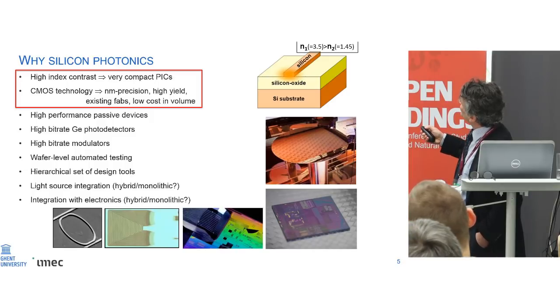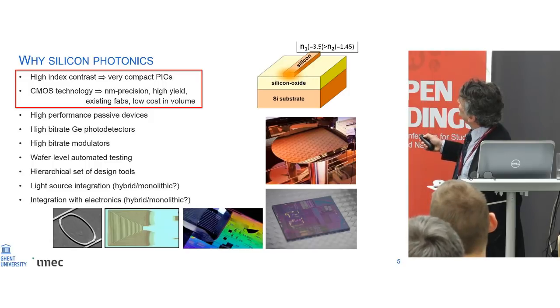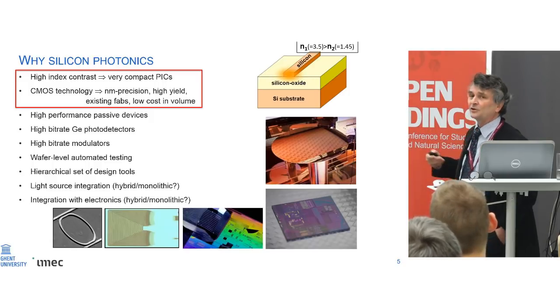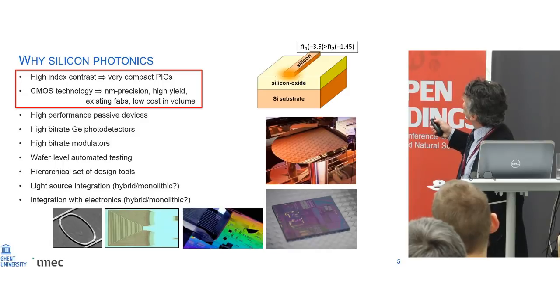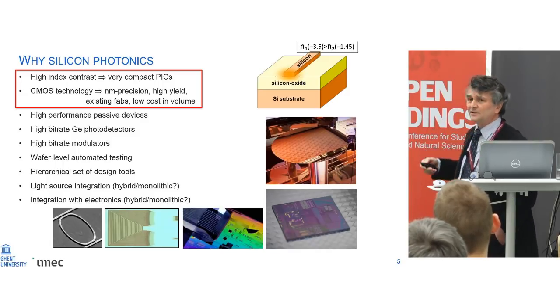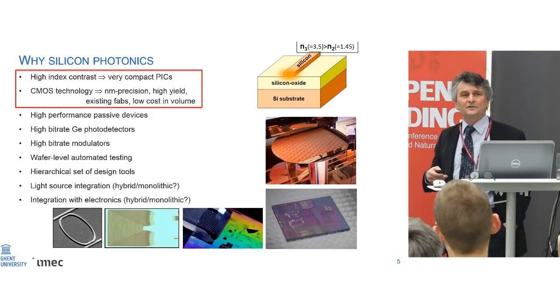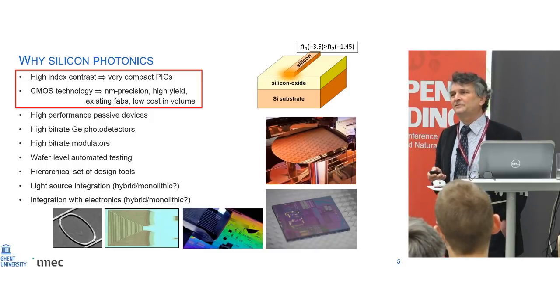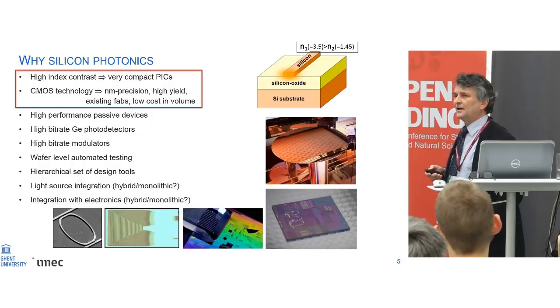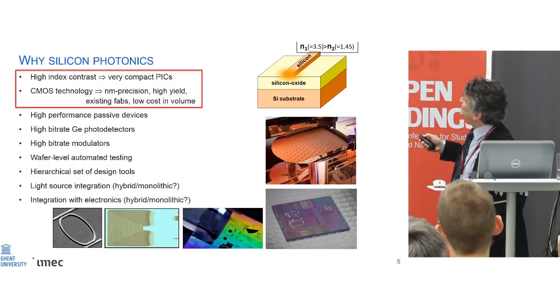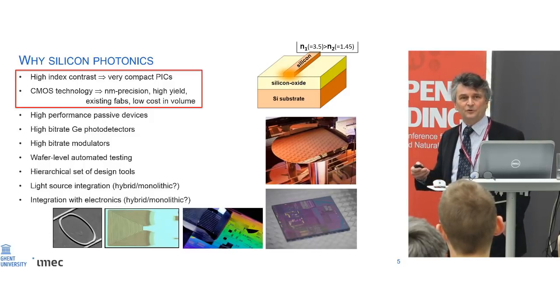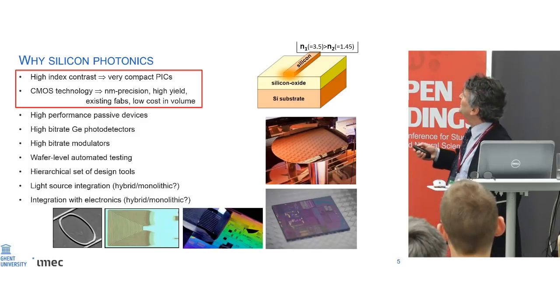And in silicon photonics, this wire of light is made of silicon, and silicon has a high refractive index of 3.5, and it's actually embedded in silicon oxide, which is glass, which has a low refractive index, 1.45. So this is a waveguide, the core of which has a dramatically higher refractive index than the cladding. And if that is the case, you can really miniaturize your photonic circuits to the extreme.